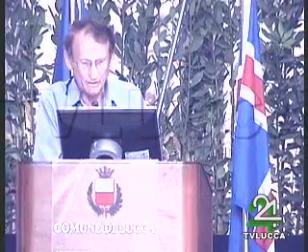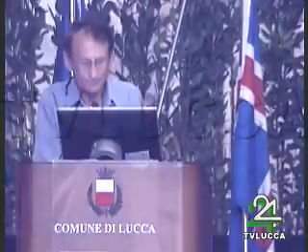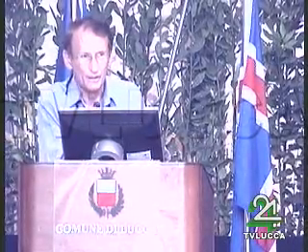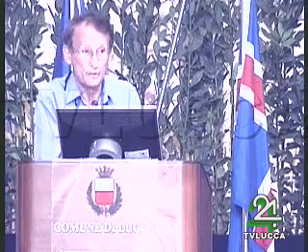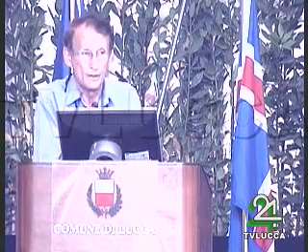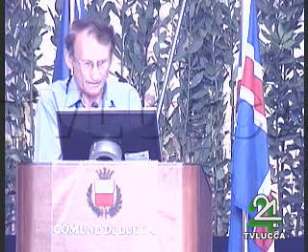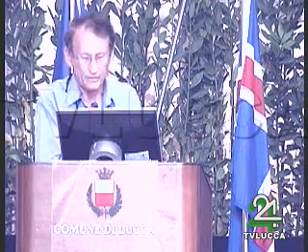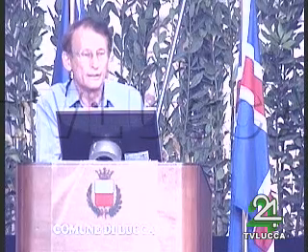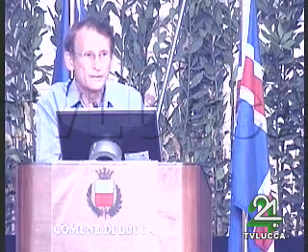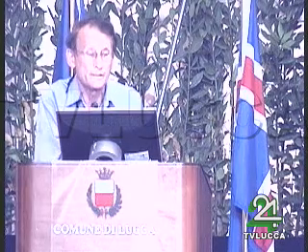Yes, with the proceeding of decomposition, we expect this. When decomposition proceeds, we have a development of the peak. The concentration of vacancies, the concentration of defective units, increases, and the peak increases in intensity.